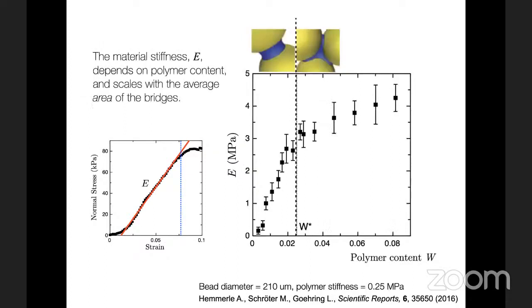We can also change the amount of polymer, and we find the interpretation of the data is that the cross-sectional area of the bridges is what determines the elasticity of the assembly. So if the bridges cover twice the area, they're twice as stiff, and so the system is twice as hard. We find that works until, if you know anything about wetting conditions, there's a transition between what's known as a pendular state, where you have rings of liquid between particles, to a funicular state where liquid will start going into the pores between particles. Above that state, the physics is different.